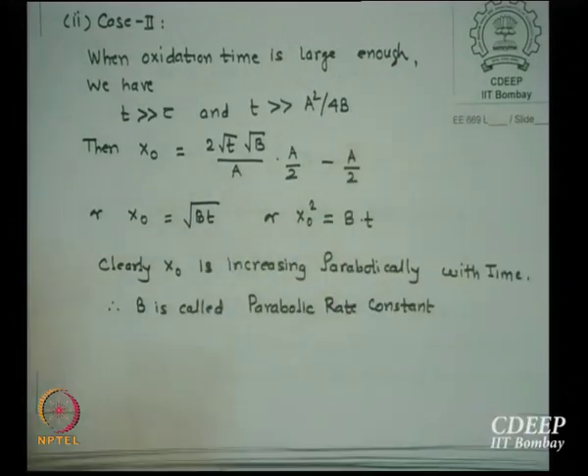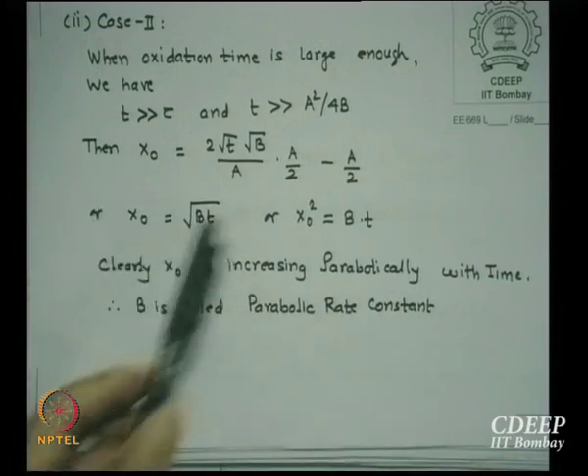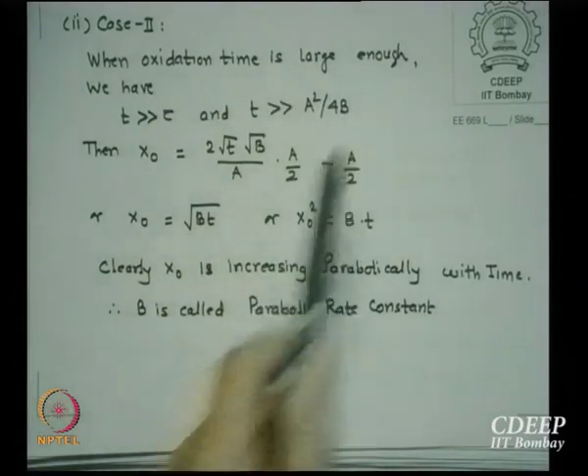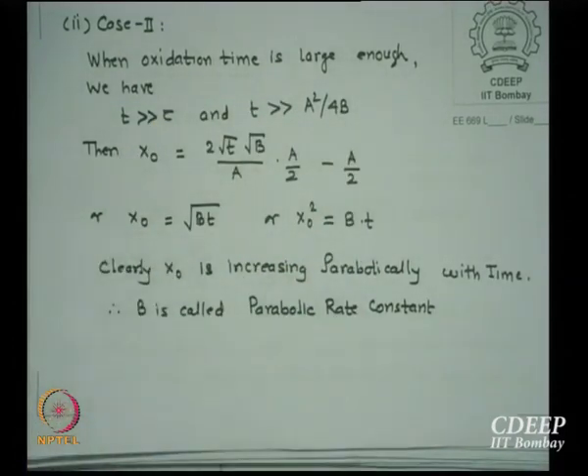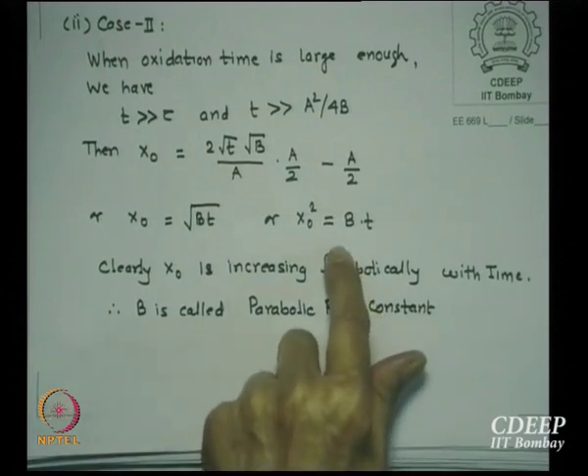We are neglecting small terms, so compared to this everything is small. This term is smaller than this, we already said through this. So we always say x0 is root of Bt, which means x0 square is Bt. What is this law? Parabola. This x0 square is Bt is a parabola.